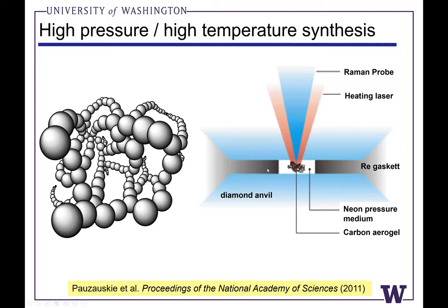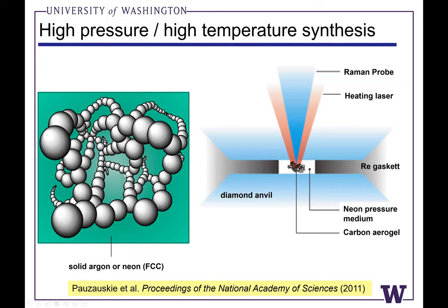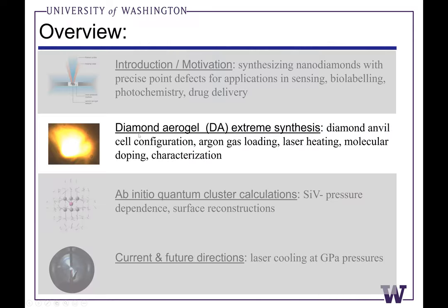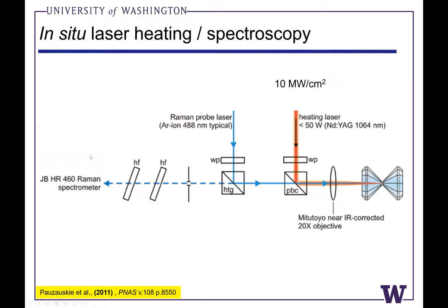We make the aerogel. Typically we'll load the interior pores of the aerogel with either neon or argon, a face-centered cubic neon or argon at high pressure serves as a very nice quasi-hydrostatic pressure medium. And then we use laser heating to drive a phase transition from amorphous carbon to diamond while preserving this sort of mass fractal microstructure of the target materials. So next, I'll share a few more details of the synthesis.